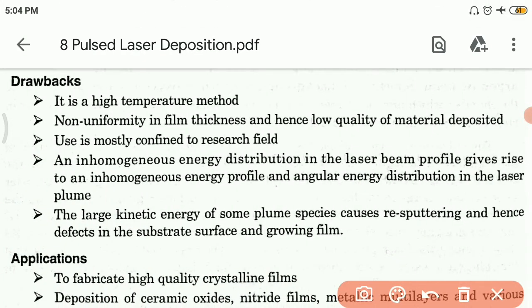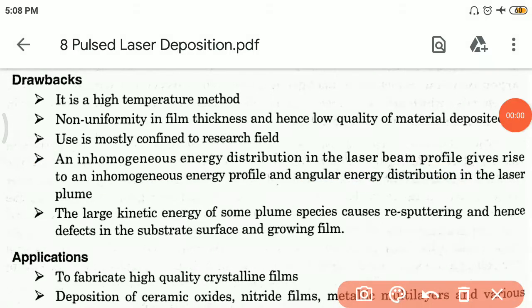Now let us see some of the drawbacks or disadvantages of this PLD technique. Number one, it is a high temperature method, so it requires high temperature. Number two, non-uniformity in the film thickness, and hence low quality of the material deposited in the film. Then use is mostly confined to the research oriented field. Then an inhomogeneous energy distribution in the laser beam profile will give rise to an inhomogeneous energy profile, and hence angular energy distribution in the laser plume. Finally, the large kinetic energy of some plume species will cause re-sputtering and hence defects in the substrate surface and growing film.